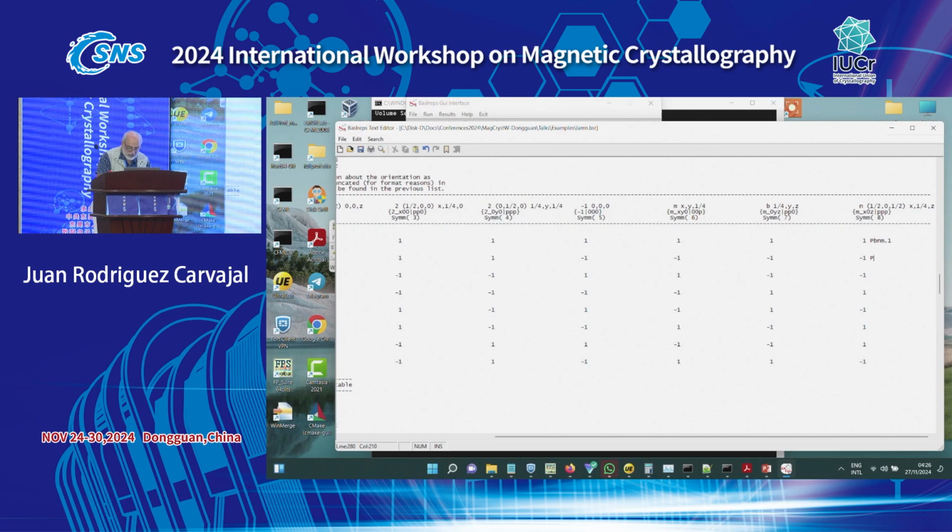Let me just put PBNM. And here you see the elements, PB and M. The generators are here at the end, and you see the character is what you have to prime. For instance, this one is the B, and here B is prime. You see that. And N is this one, is also prime. And M is this one, is also prime.